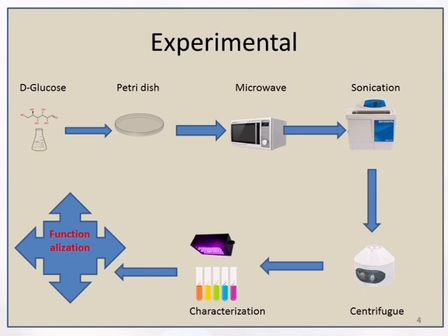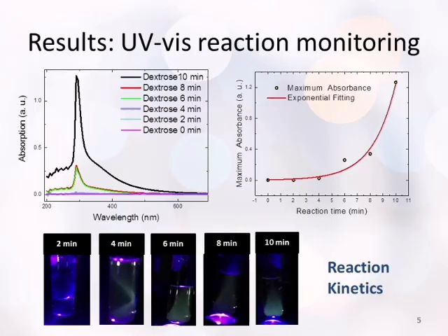After the reactions were stopped, we recovered the products into an aqueous solution and sonicated it for 30 minutes. Then we centrifugated them to separate clusters, and we are today characterizing them. Later, carbon quantum dots are going to be functionalized to be used as cellular biomarkers.